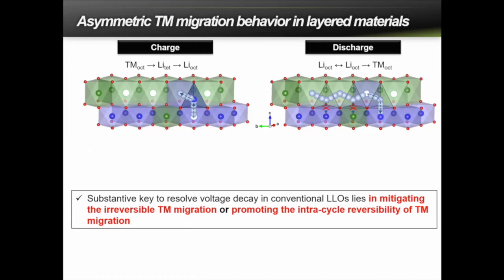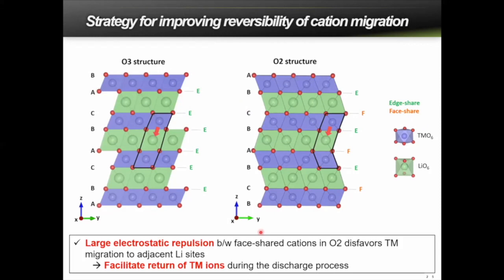If the transition metal migration to the lithium layer is almost inevitable because of the thermodynamics, we thought that the substantive key to minimize this negative effect is to streamline the structure so that transition metal migration only occurs at this path. So it comes up, but it doesn't get distracted, and it comes back. So that the transition metal migration occurs only at this path and inhibits other paths like this in-plane migration in the lithium layer. And if we can lock here, then the further migration of transition metal is going to be inhibited. So then how do we do that? Then how do we actually ensure the transition metals do not go astray in the vacant lithium layer and readily come back to its original site when lithiums are reintercalated?